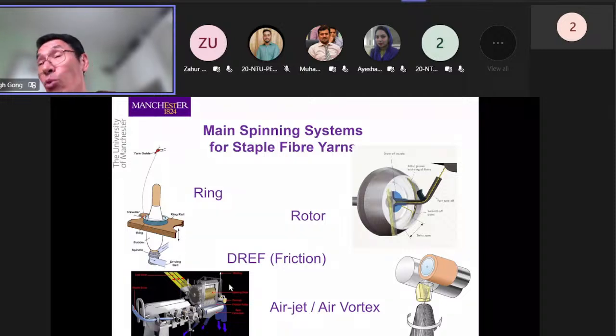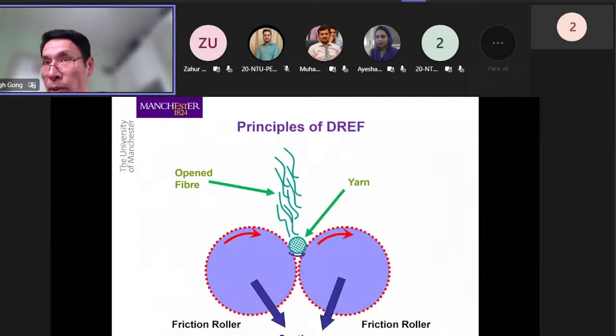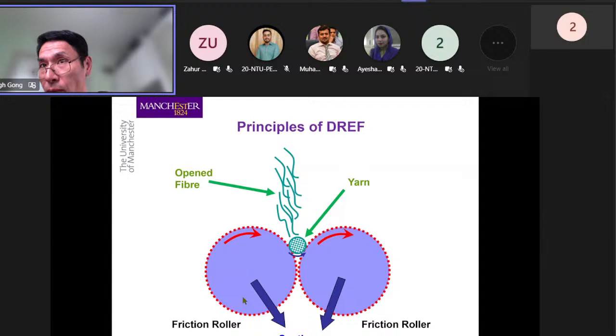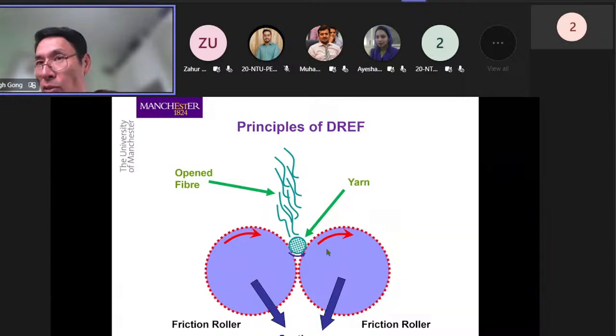So in the end, we realized friction spinning is probably the best in this case. There are other people trying other methods, but for what we have evaluated, we have decided that friction spinning is more suitable because the idea of friction spinning is very straightforward. So you have two suction rollers, essentially, and they provide also friction to the yarn surface. And then you just need to spread the open fibers into this twisting zone, and then the fibers will be gathered up into a yarn. So you withdraw the yarn, in this particular case, perpendicular to the screen, so drawing it out parallel to the rollers, and that's all. So in terms of principle, as you can see, it's very straightforward.